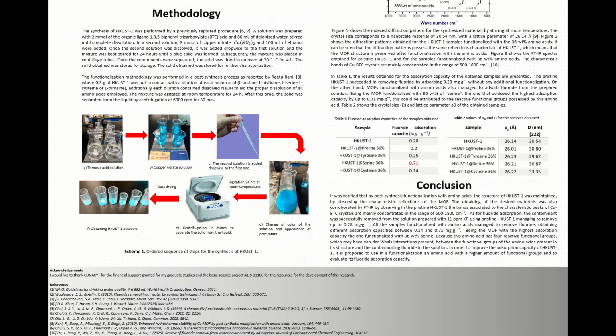Finally, as conclusions of this research project, it was verified that by post-synthesis functionalization with amino acids, the structure of HKUST was maintained, by observing the characteristic reflections of the MOF. The obtaining of the desired materials was also corroborated by FTIR, by observing in the pristine HKUST the bands associated to the characteristic peaks of copper BTC crystals, mainly concentrated in the range of 500 and 1,800 centimeters. As for fluoride adsorption, the contaminant was successfully removed from the solution prepared with 11 parts per million of potassium fluoride.